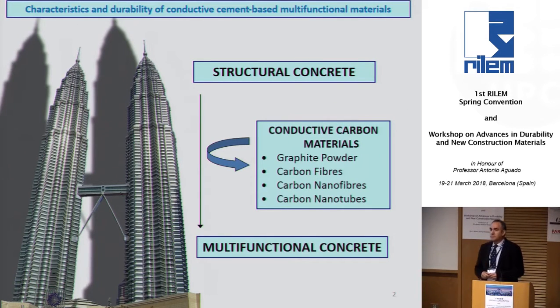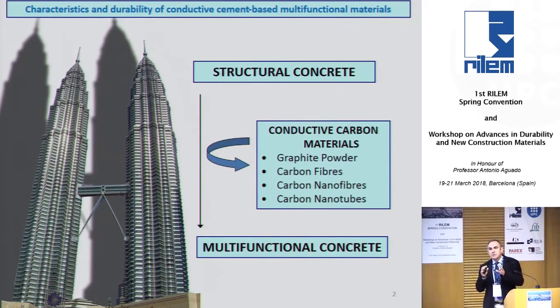It is widely known that the main function of concrete is a structural function. On the other hand, concrete is a dielectric, a bad conductor of electricity. However, the addition of conductive carbon materials such as graphite powders, carbon fibers, carbon nanofibers, carbon nanotubes transforms the resulting mixture into a conductive material. And this yields the possibility of using this material for functions other than structural ones, so that it can be considered a multifunctional concrete.